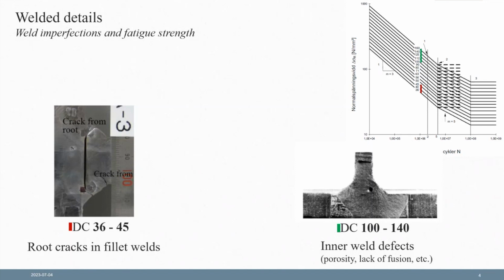The second category that we can identify belongs to details that have very high fatigue strength. In this category, usually the fatigue crack starts from inner weld defects or inner weld imperfections, such as porosity, lack of fusion, and so on. And typically, these are not determining the design of steel bridges, for example. They have such high fatigue strength that they are not setting the roof in the fatigue design.